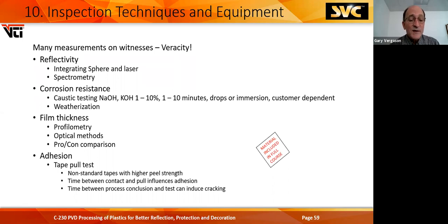Film thicknesses, we use profilometry here. We also have optical methods, and there's pros and cons comparing the different methods. Adhesion, most adhesion tests, believe it or not, are the old tape pull test. You cross-hatch the part, cut through the coating into the substrate, put the specified tape on, rub it, let it set or not. There are specs and tape tests, and rip it off and look for how much, if any, of the coating came off.